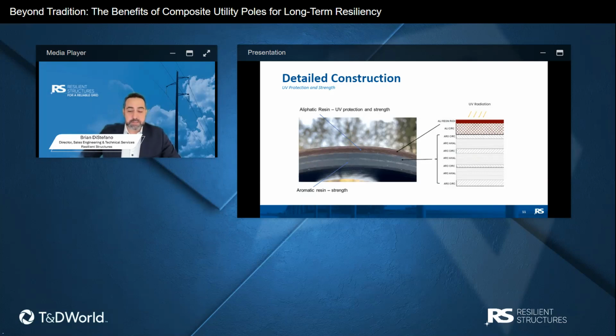UV exposure is the primary cause of composite degradation. All composite poles include some form of UV protection. They must. So a lot of manufacturers will actually apply a thin UV resistant paint that's microns thick. Our product features an integral outer layer, 1 to 2 millimeters thick, of aliphatic resin, ensuring that the pole doesn't chip or require any kind of periodic reapplication.